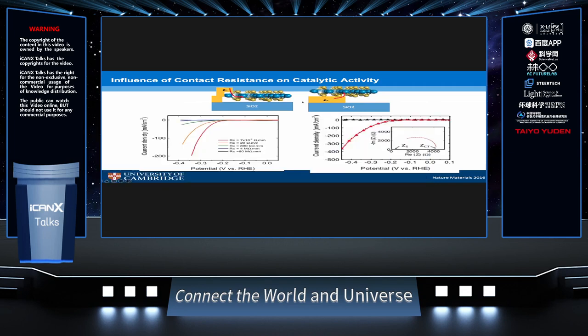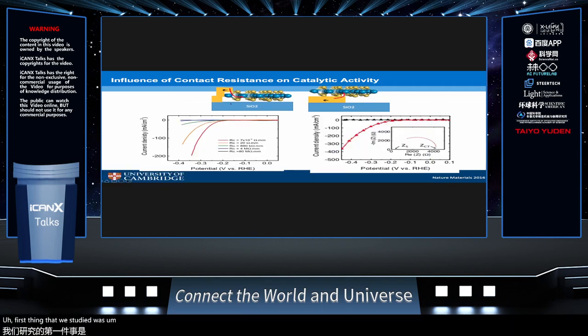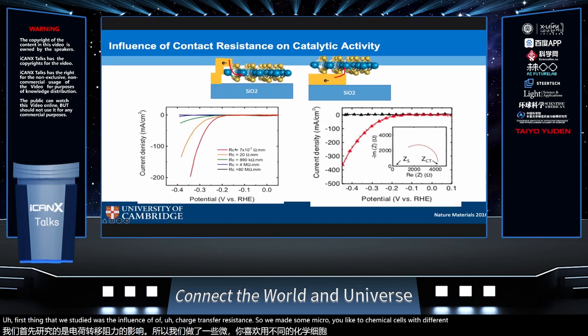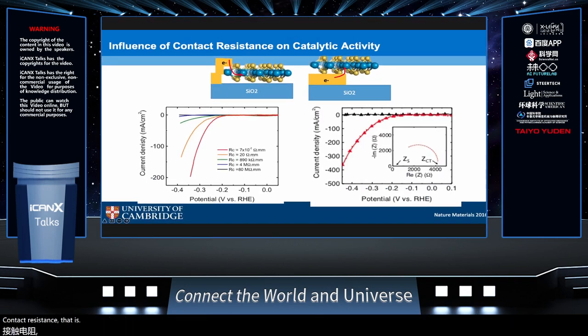The first thing that we studied was the influence of contact resistance. So we made some microelectrochemical cells with different contact resistance, that is the resistance between the catalyst and the substrate. One can do this by lithographic patterning and by phase engineering. You can tune the contact resistance and study its HER performance. And it's not surprising that the device with the lowest contact resistance gives us the best catalytic activity, right?